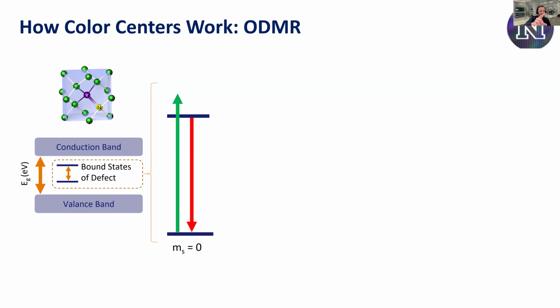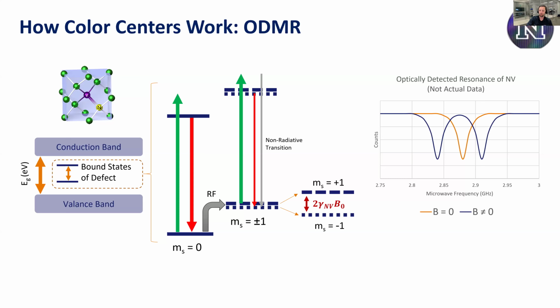So that's what we're seeing here on the right. As you scan the microwave frequency, you can see that when you're on resonance with that transition into the plus or minus 1 spin state, if you have no magnetic field, you see this dip in emission, right? Because of the non-radiative transition. However, when you then apply a magnetic field, it splits that, and now you actually get two dips depending on the microwave frequency. And so by manipulating this and using pulsing schemes and all sorts of things, you can use this as a really clever magnetic sensor. But again, I'm just a lowly material scientist. That's not for me. I just want to etch things.